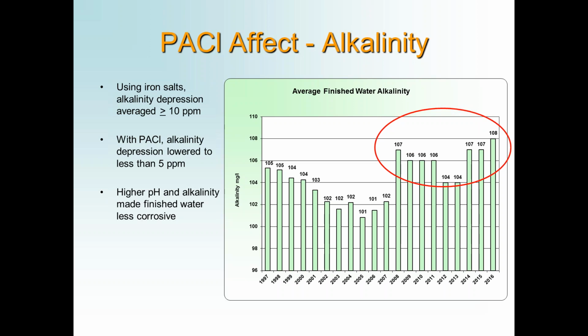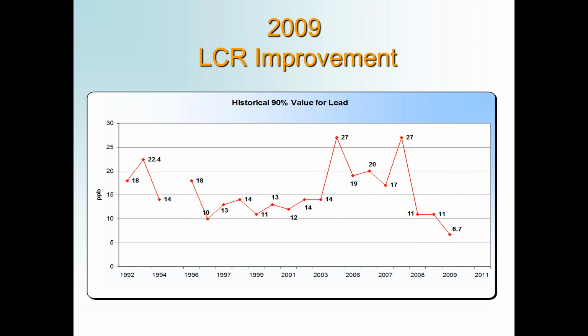So we like to believe, from what the evidence shows us, that even that slight change in pH and slight change in alkalinity brought us back into compliance. It was just enough to force the phosphates to work better. Looking at 2009, you can see our 90th percentile now dropped to 6.7, a further improvement in the lead levels in our first draw sampling program.